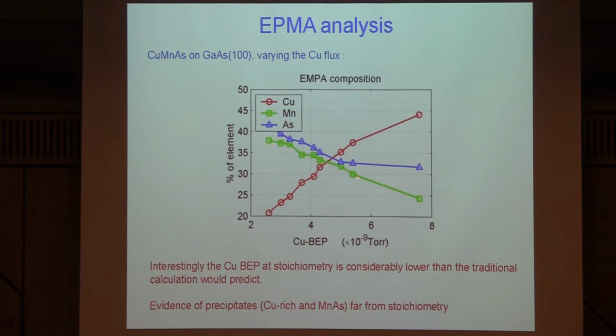This is where we want to grow, that's fine, but it's also kind of interesting in that the arsenic is pretty much flat. It wants to be around about 33%, and it is around about 33%, so that makes lots of sense, even when there's large amounts of excess copper, which implies that the copper is not forming copper arsenide. Actually we found out subsequently that it's forming just copper precipitates. The material just simply rejects the copper, and it precipitates as little crystallites. Okay?